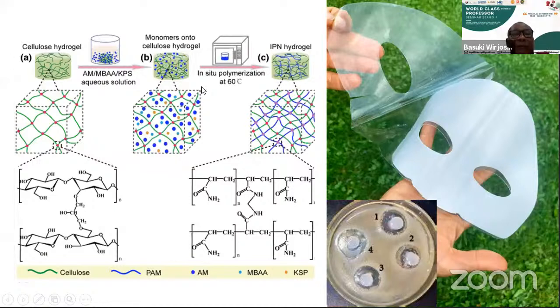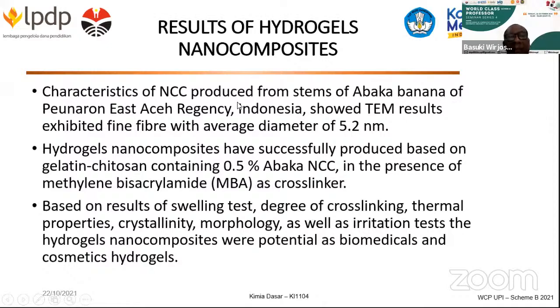Hydrogel from gelatin base and chitosan base, especially for cosmetic hydrogel, from masks and everything. Okay, and the result here is that the nanocrystal cellulose, produced from abaca banana from Aceh, gives us very fine fiber with a diameter of about 5.2 nanometers, very fine.